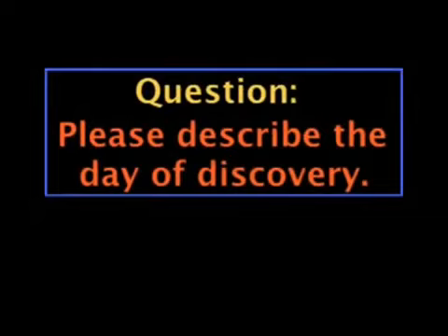It was in the morning. I was alone in the electron microscope room looking at a new material that I just created, composed of aluminum and manganese. Right there, in the beginning of the morning, I looked at the material and it looked very strange to me. And I took a diffraction, an electron diffraction from that area that looked strange. And lo and behold, I see a diffraction pattern that has 5-fold rotational symmetry.